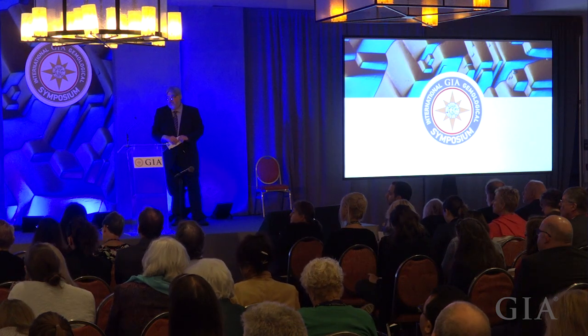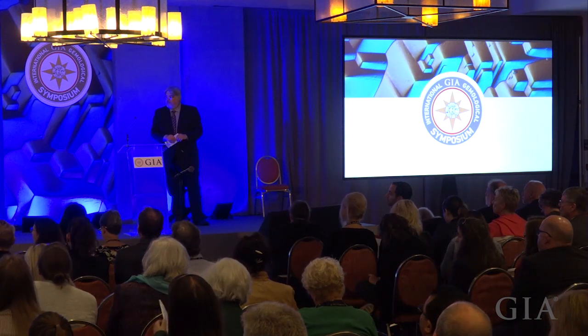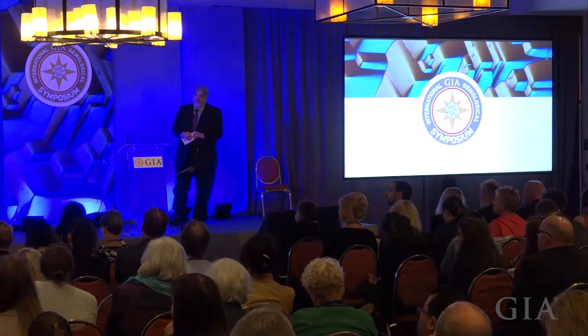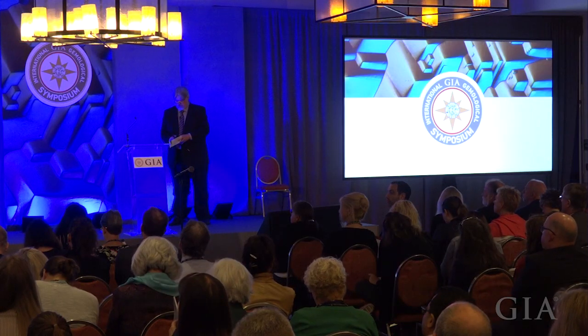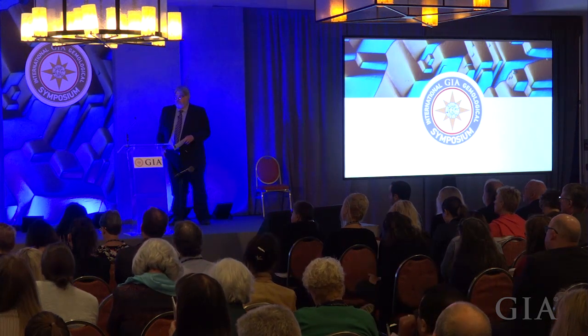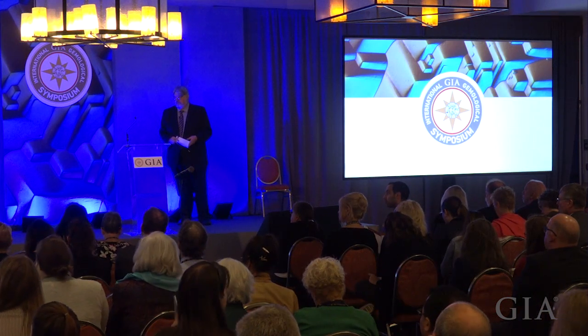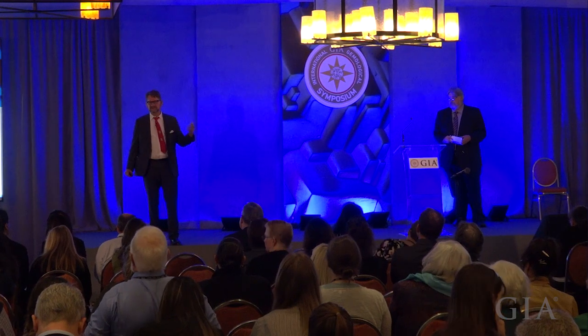So we have another example in a totally different gem, which was under high pressure, where you do find actually not as large voids, but, well, actually in the case of that particular diamond, yeah, they were very large voids, but that's totally exceptional. And these are diamonds, you know, the mixed growth diamonds. So they are not exactly your run-of-the-mill diamond. They have the hydrogen rich and all that, so we don't know much about actually how they grew, as you well know, I think. Because hydrogen-rich diamond, or cuboid growth sectors, is almost a different material from your normal octahedral diamond. So there are too many things that are unknown to really come to a coherent conclusion on that. But it's true that it's funny to find empty spaces. That's why it took so long to recognize that, I think, because people are not ready to admit that this was empty.